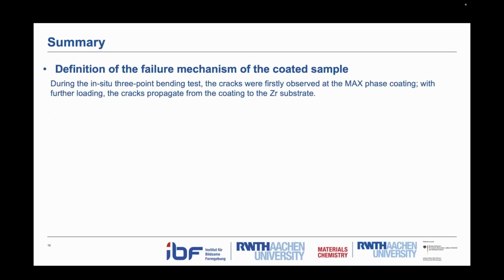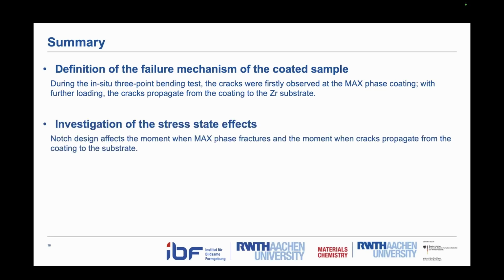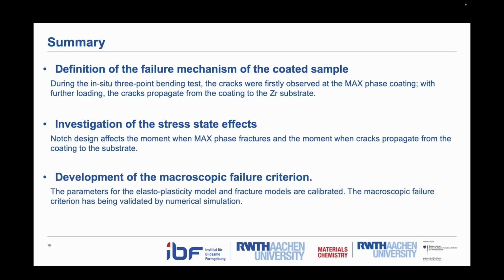So from this investigation, what we have concluded is that, first of all, we defined the failure mechanism of the coated sample: the cracks initiate at the coatings, and then with further loading, the cracks propagate from the coatings to the substrates. And we investigated the stress state effects by designing different kinds of samples, and we found that the notch design affects the moment when the coating cracks, when the coating fractures, and when the cracks propagate from coating to the substrates. And finally, we developed the macroscopic failure criterion and also calibrated the corresponding parameters. We managed to validate this work by replicating the material failure that we have observed during the test.